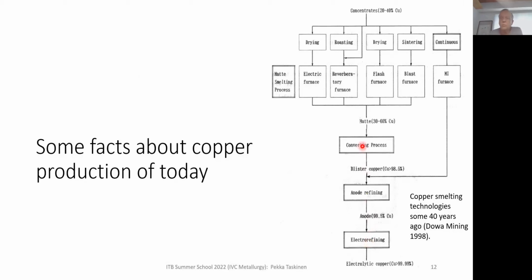So as you may know, we have had, not having any more, but we have had several options for making the concentrate smelting into matte. And this is the selection of some 40, 50 years ago, or even 70 years ago, when the flash furnace was included. Most of them have been disappearing. So the remaining technologies are either not listed here, or they are these two actually, flash furnace and Mitsubishi furnace.